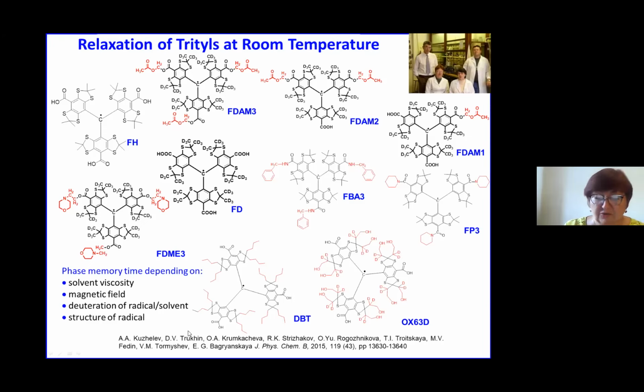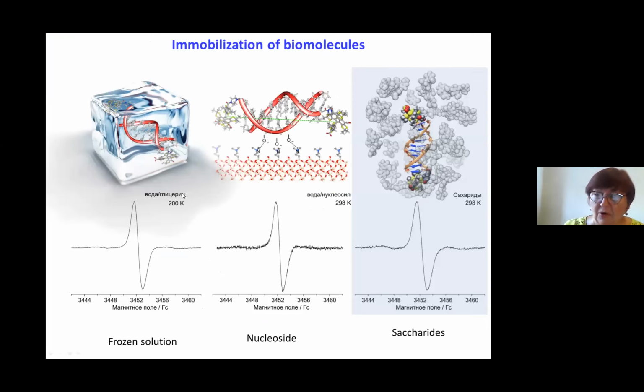he can do it. So we, together with a team in ITC, investigated electron spin relaxation and the mechanism of electron spin relaxation and such things. So we have the possibility to choose either to use this OX063, which is non-toxic, water-soluble, or the quite simply synthesized FD radical. So we have this privilege in our institute. Another point is immobilization. As I said before, if we would like to measure at room temperature, we need to immobilize this molecule. In water-glycerol solution one can measure only at temperatures lower than 200 kelvins, while at room temperature we have to immobilize, and one can immobilize in nucleoside or some silica gel, oligonucleotide, or in saccharides. In particular, we use trehalose.